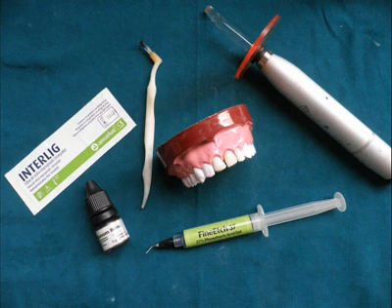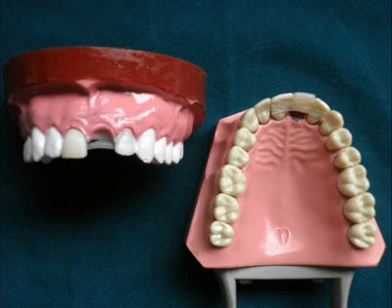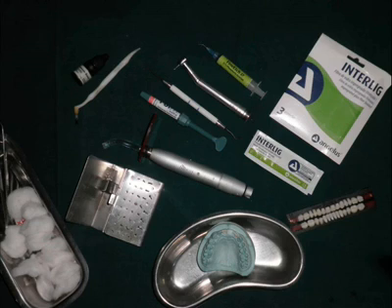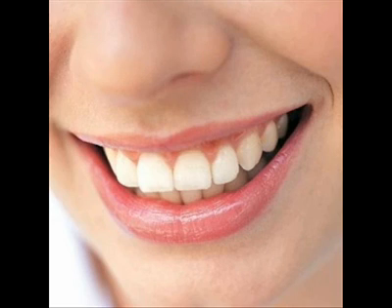The combination of restorative resin, adhesive system and fiber reinforcement has introduced a new generation of metal-free, conservative and immediate restorations of missing spaces. The importance of using such high quality and proven materials and their correct clinical use needs to be emphasized. Currently acceptable success rates in long-term FRC restorations such as crowns and bridges have been reported. However, the utilization of this technique seems to be viable mostly in non-stress bearing areas, highly esthetic areas like the upper and lower anterior region.